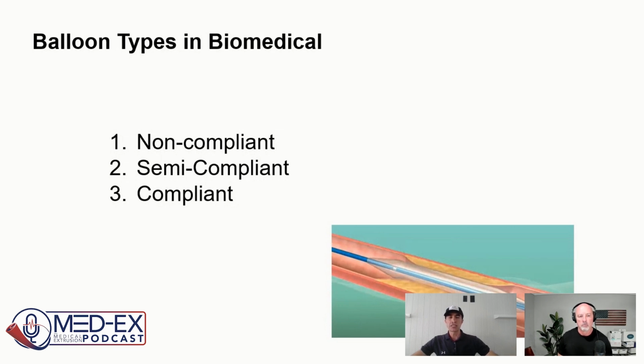Semi-compliant balloons, on the other hand, are a little bit more flexible. They are made of materials like PEBAX. They are more flexible, and that's when you need some flexibility. So you need pressure, but at the same time, you need some kind of diameter growth, and that's where you're going to go up to about 8-10% of your diameter.